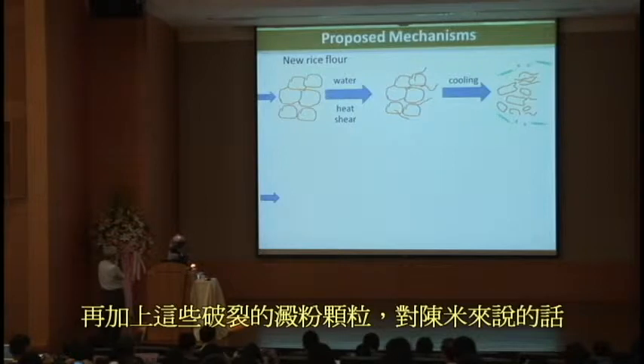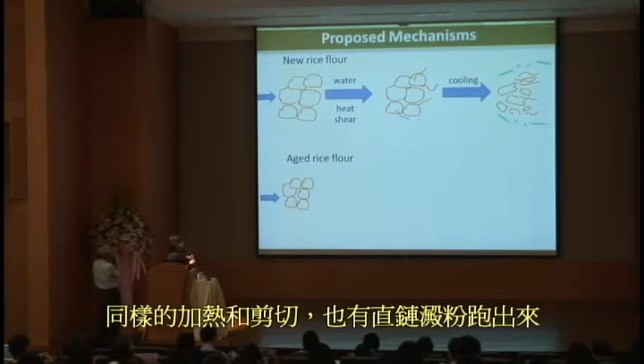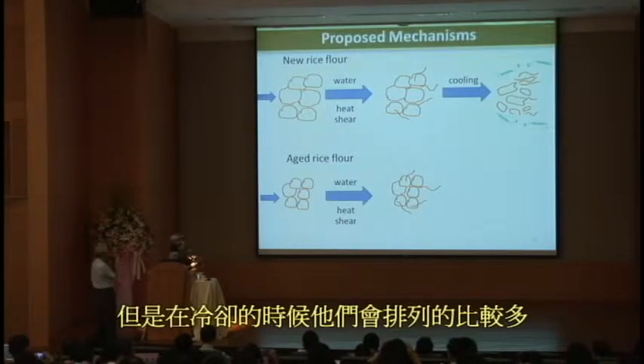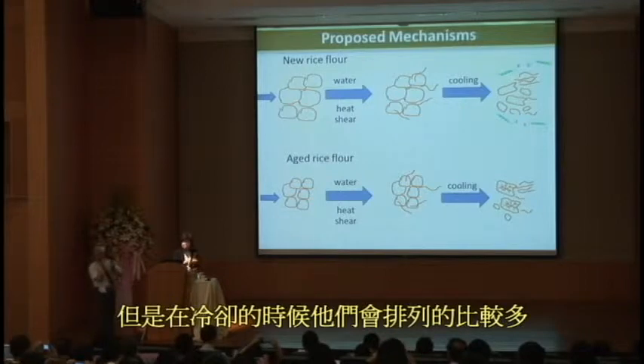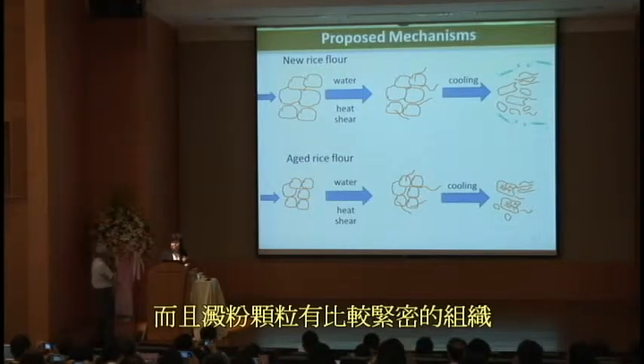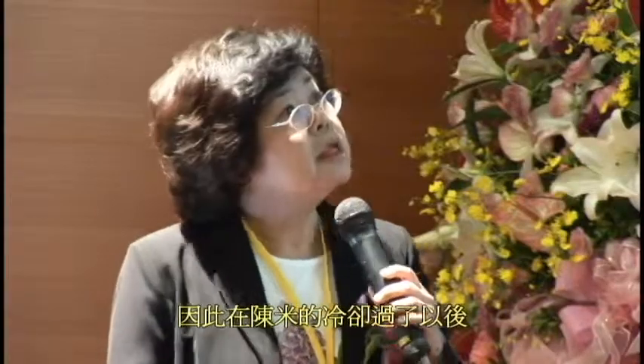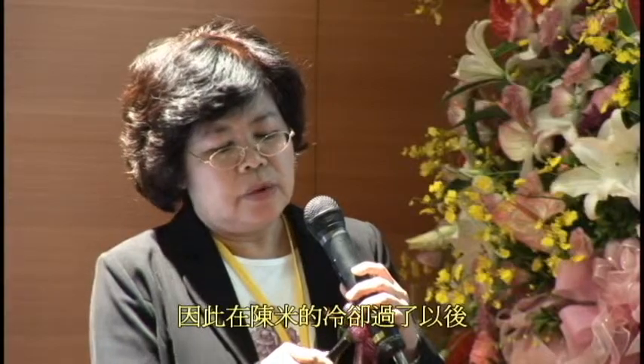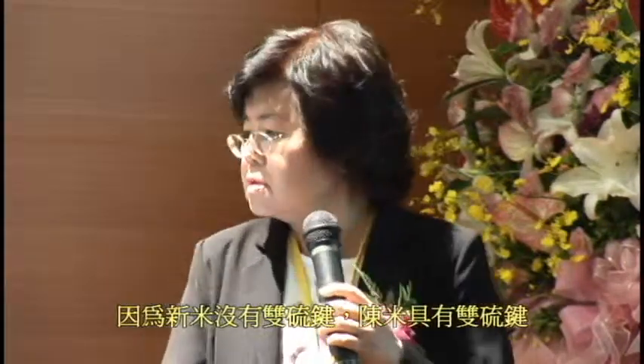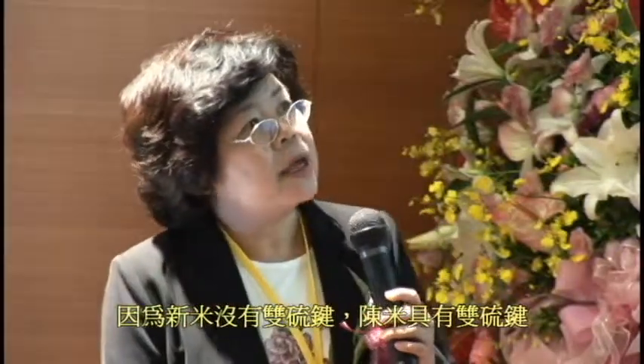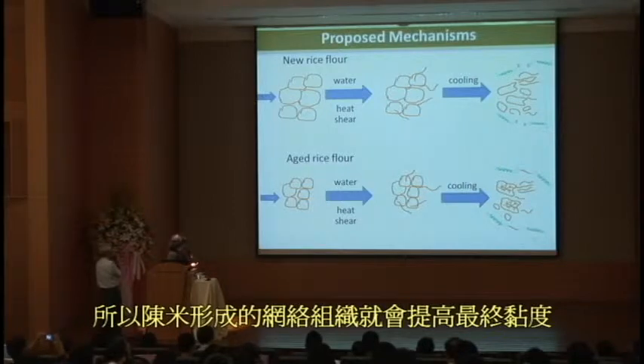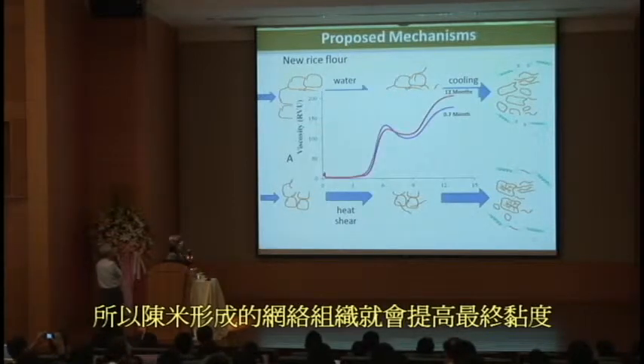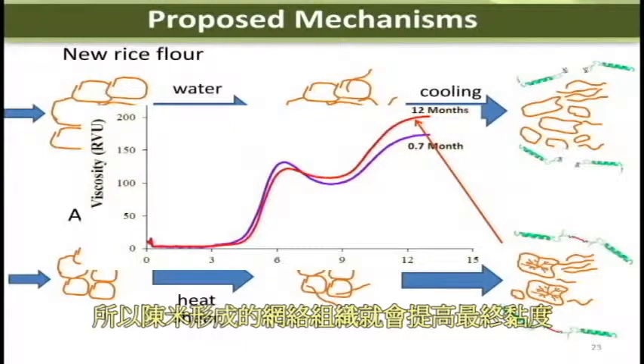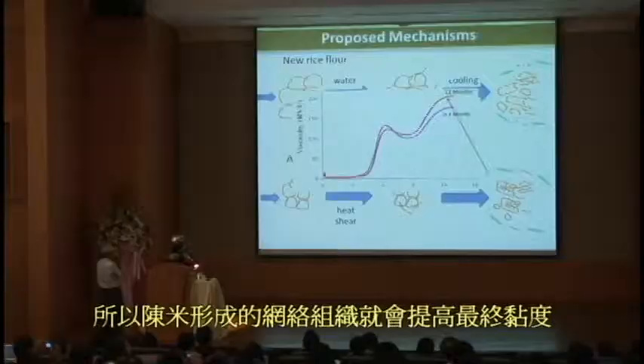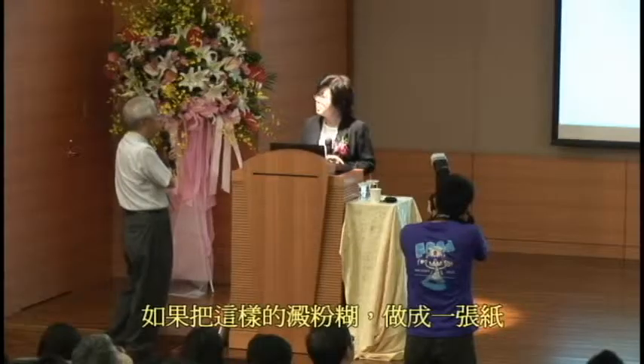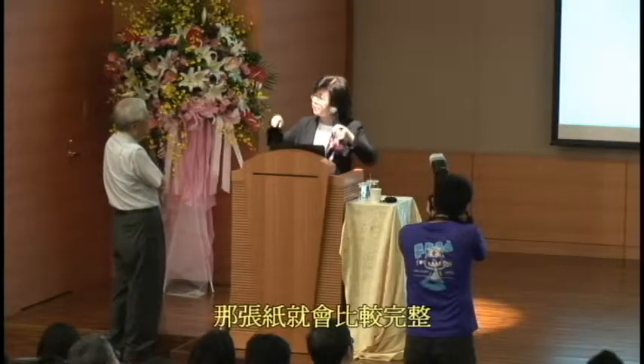But for the aged rice flour, the swelling is less. Also amylose leaches out, but the disrupted granule is less than the new rice flour. And the protein in the matrix for the new rice doesn't have the disulfide bond, but the aged rice has disulfide bonds. So with this event, we can see that after cooling, the final viscosity of the aged rice flour is higher than the new rice. And this makes the noodle sheet a more perfect sheet.